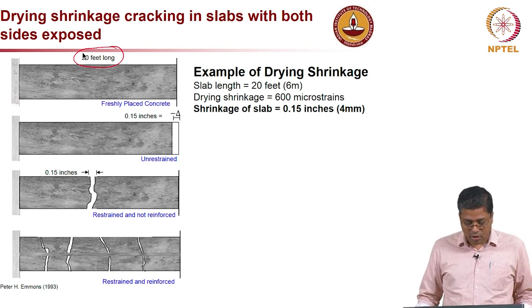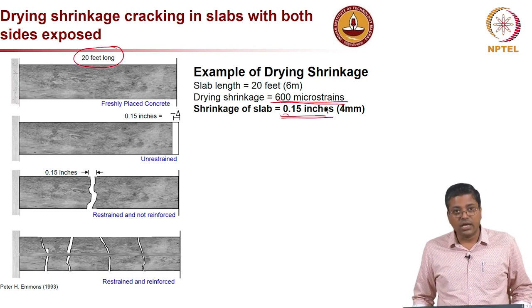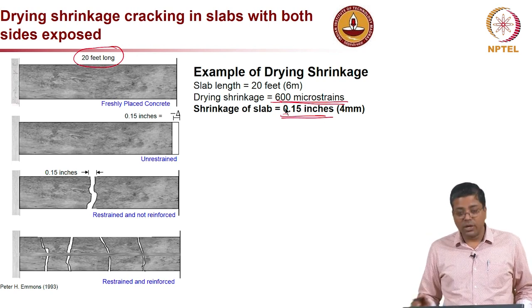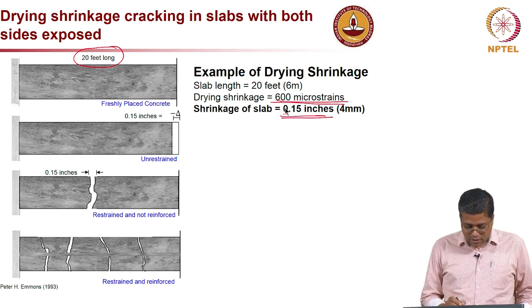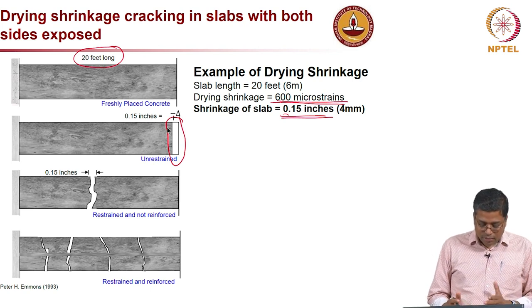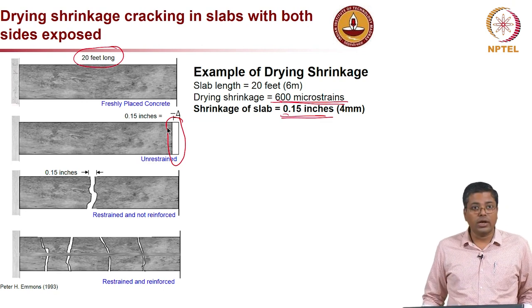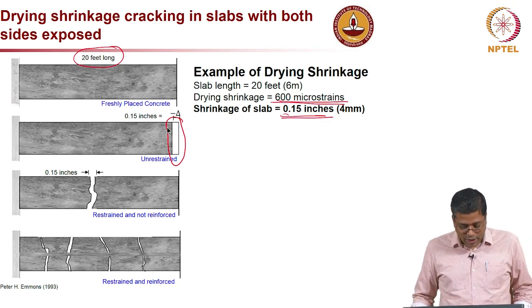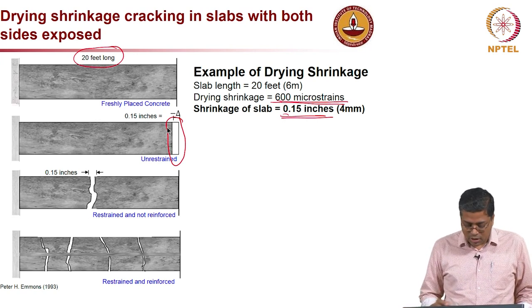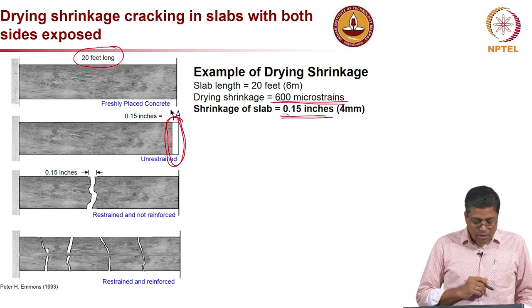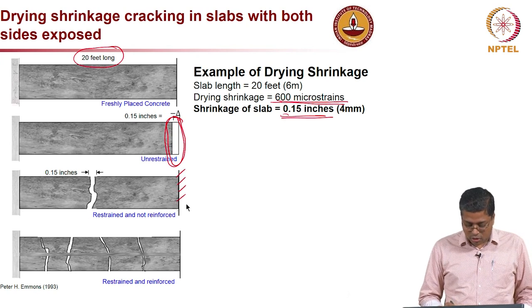You can see here the element is 20 feet long, and if the drying shrinkage is about 600 microstrains, the change in the axial length could be about 0.15 inches. That is shown here, this is the reduction in the length. Now if it is unrestrained concrete, where both sides are not held together and free shrinkage is allowed, the length change will happen like that.